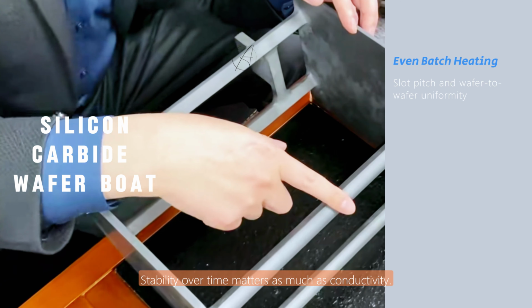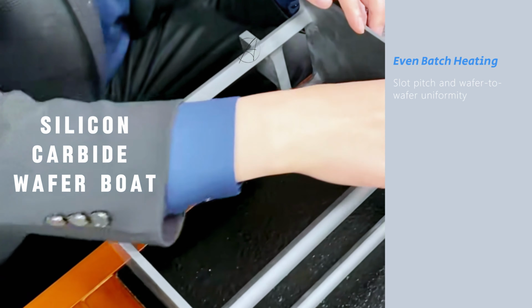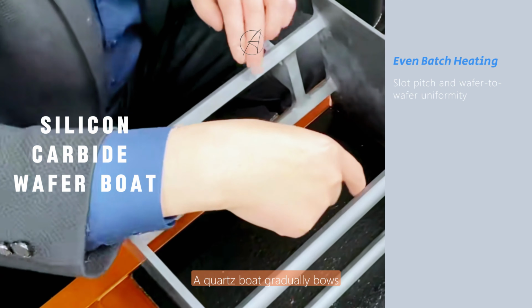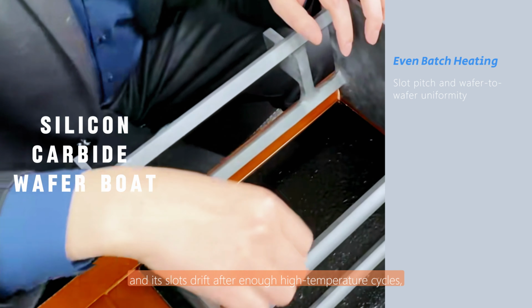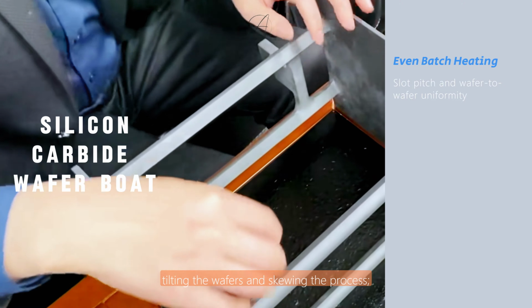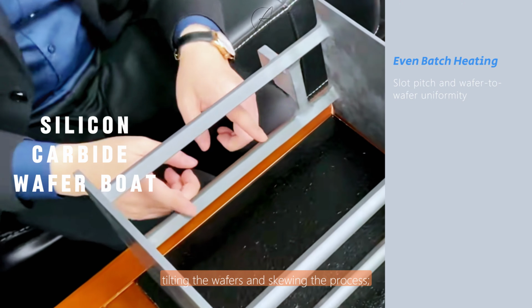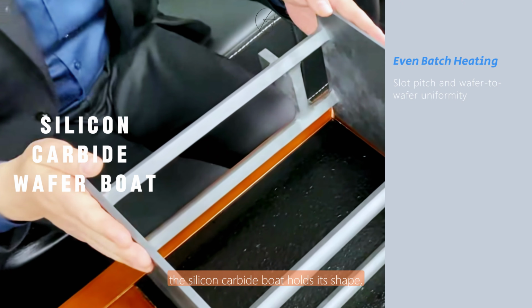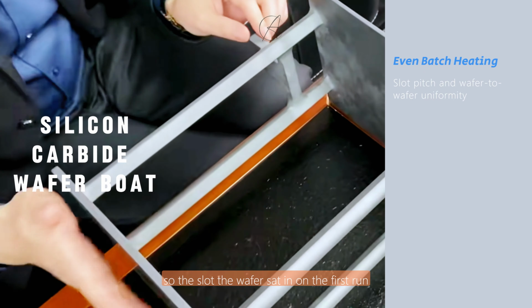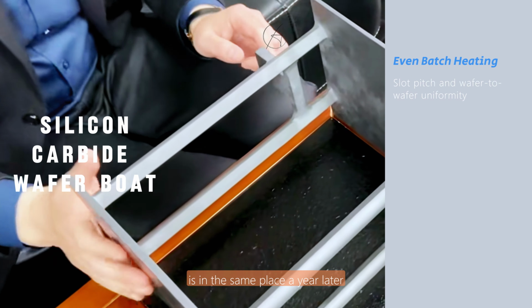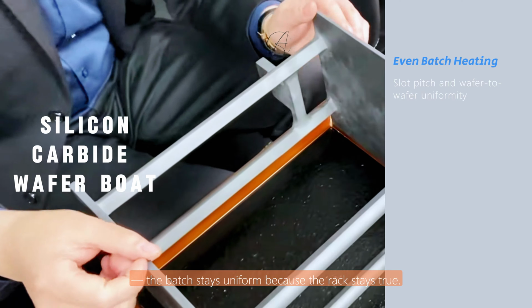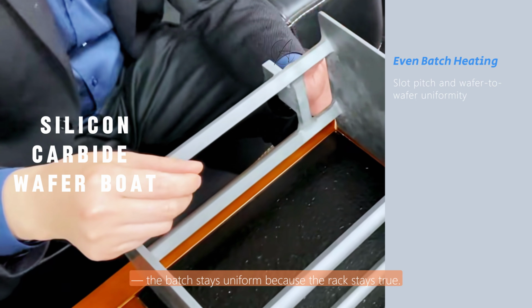Stability over time matters as much as conductivity. A quartz boat gradually bows and its slots drift after enough high-temperature cycles, tilting the wafers and skewing the process. The silicon carbide boat holds its shape, so the slot the wafer sat in on the first run is in the same place a year later. The batch stays uniform because the rack stays true.